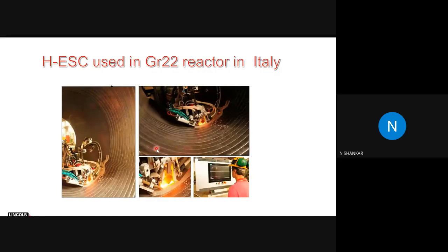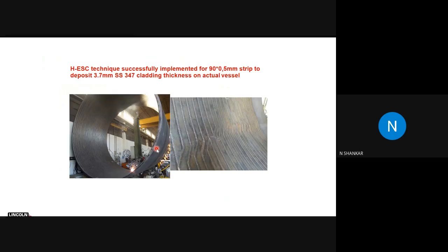This is a 2.25Cr reactor, which is cladded with the hybrid process in Italy. Here is a 347 cladding material where cladding was done with the hybrid electroslag cladding application actually. Here we used a 90 mm strip, 0.5 mm thick, to deposit a 3.7 mm overlay height. Actually, that's what was deposited.